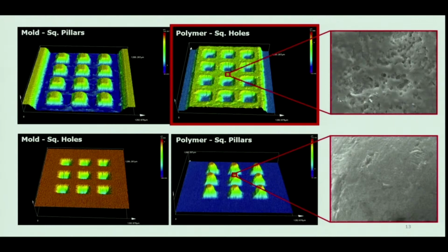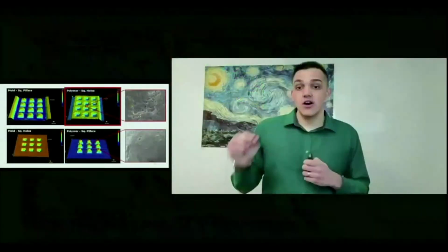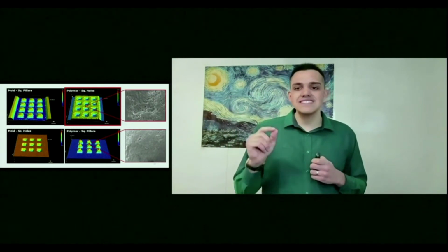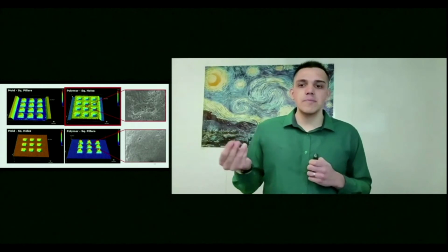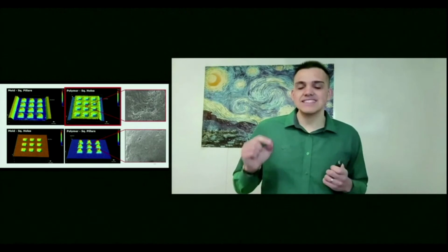And then, after successful replication of hierarchical structures on the polymer for square holes, the plastic sample will be tested in the goniometer, which is an equipment that measures the degree of hydrophobicity of a sample. And then I will move on to test the other geometries from scratch. And ultimately, the best laboratory performances will be evaluated in the injection molding at our industrial partner.